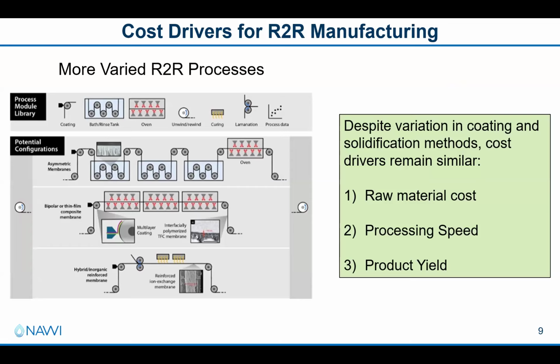So you could have a system set up with coagulation baths so that you can make asymmetric membranes for either liquid or gas separation activities. You could have simultaneous multi-layer coating activities. Or here you could be making things like bipolar membranes for different bipolar membrane electrodialysis processes. Or you could be thinking of trying to make interfacially polymerized thin film composite membranes. Or maybe you feed a substrate through your coating process and then wet laminate in mesh support to make various different kinds of supported membranes, whether they're ion exchange membranes or other kinds of separation membranes, before you feed it through a solidification process and get a membrane out on the other side.